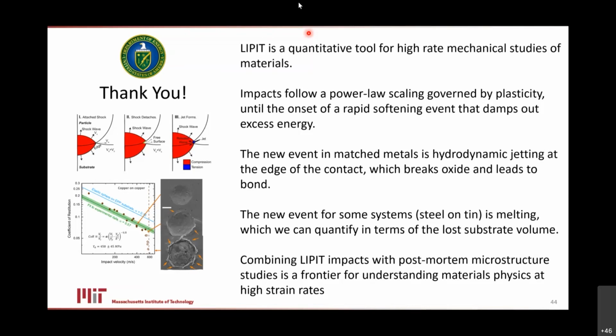That's a good question. It is sort of an interest of mine to study chemical reactions during these impacts. The timescales are very short, as the question suggests. You've got a couple hundred nanoseconds of total action for some kind of reaction to happen, but that could be enough time. So there's time, there's heat, there's pressure. We have done some cases where we shoot mismatched pairs together, like copper and aluminum, and we definitely see intermetallic reactions at that interface. So it's possible to trigger reactions. It's possible to trigger phase separation. I can't say that it's well studied, but it is a pregnant topic, I would say. So it's a good question.